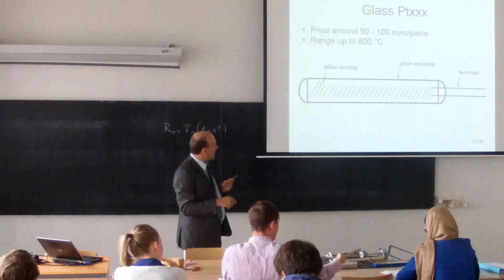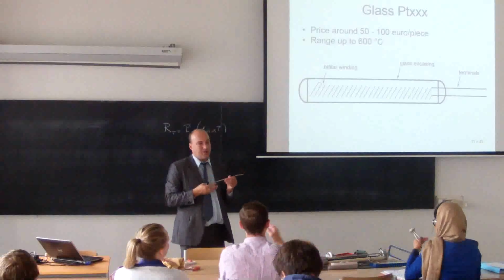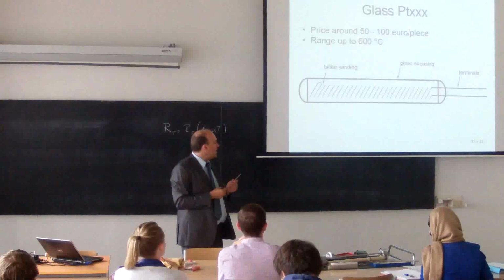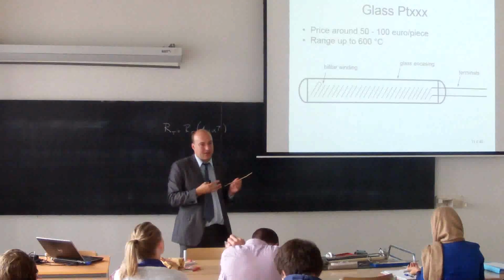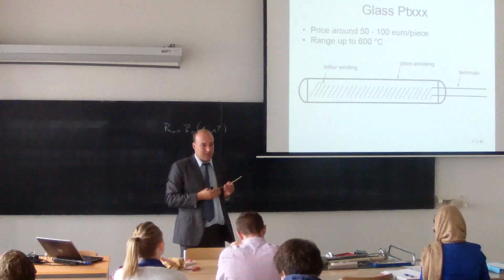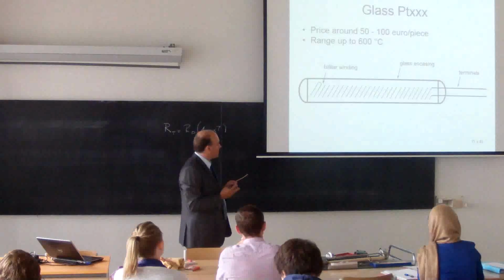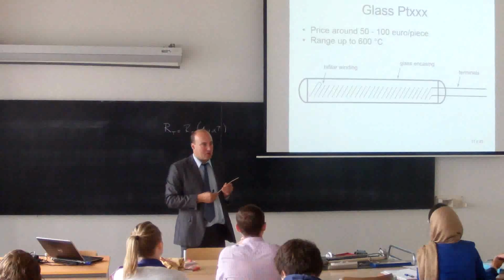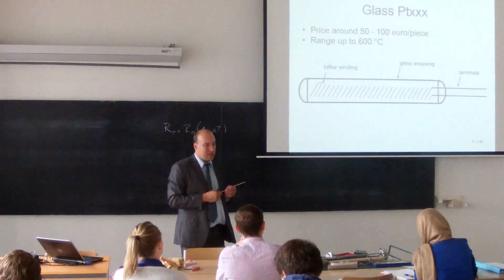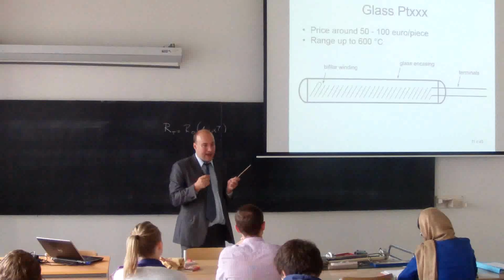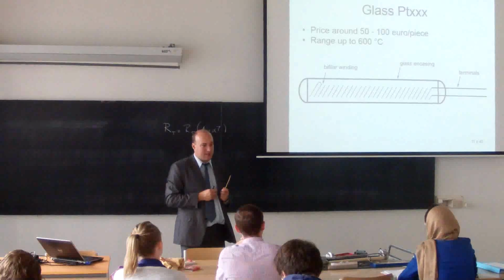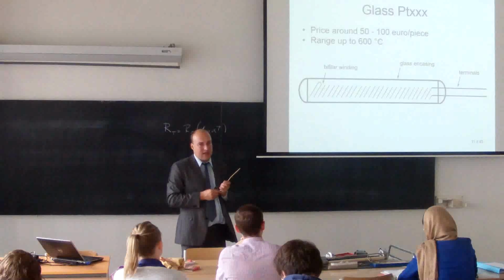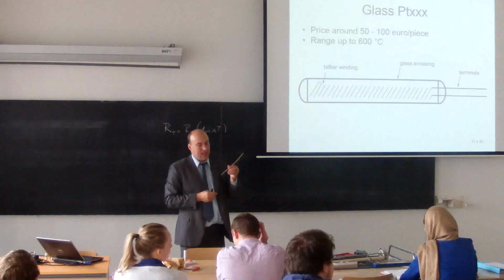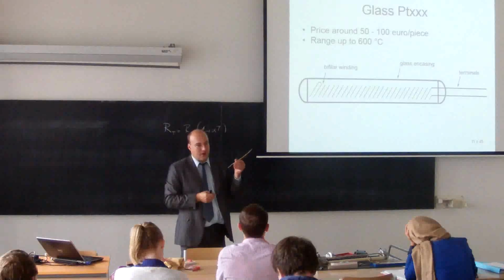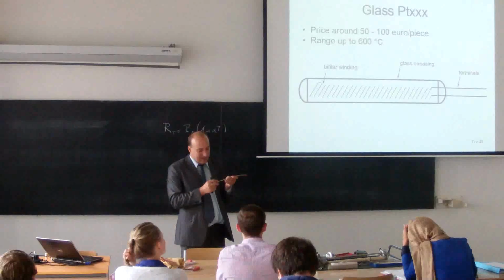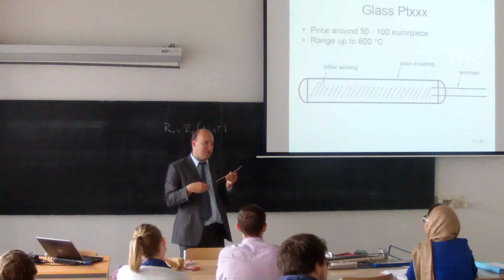The glass encases completely the platinum wire, and the thermal expansion of the platinum is different from the thermal expansion of the glass. So there will be something that is called a strain gauge effect. It will also limit this temperature range. It means that we will stretch the wire and we will change its electrical resistance. So those are the problems of the platinum wire encased in glass. Glass is really fragile, but it's less expensive to produce with glass than with some other materials.